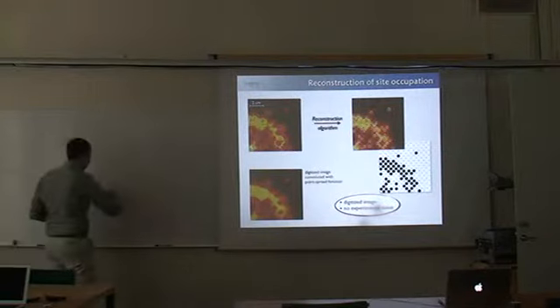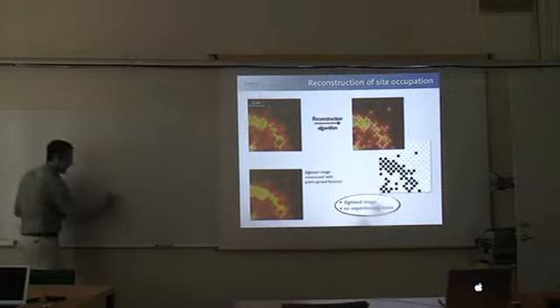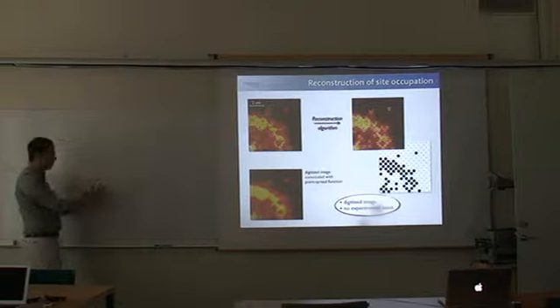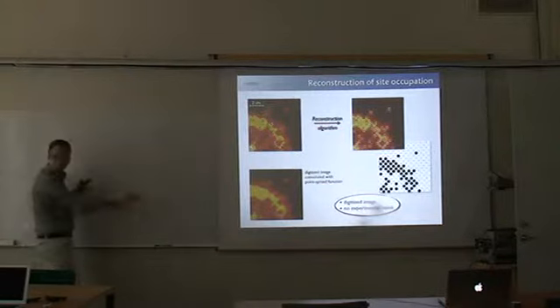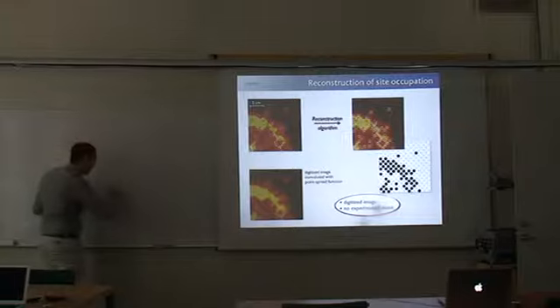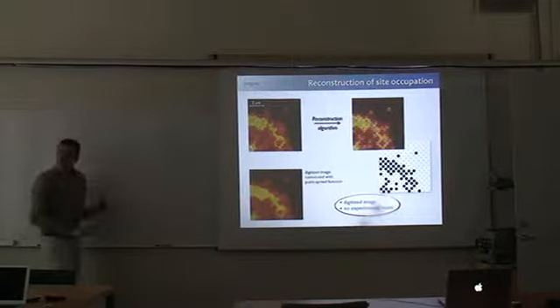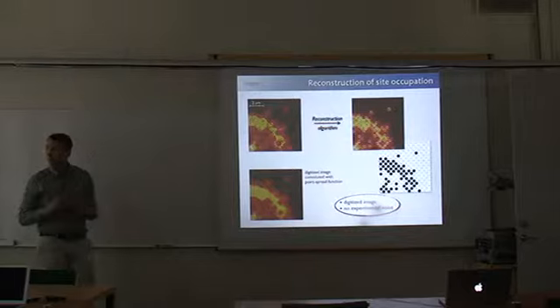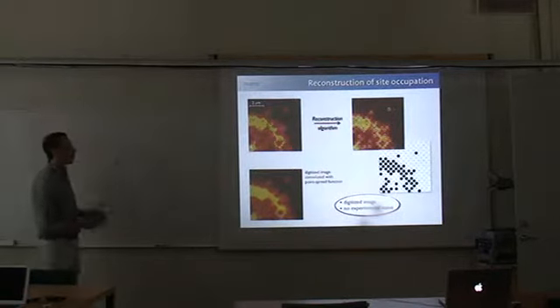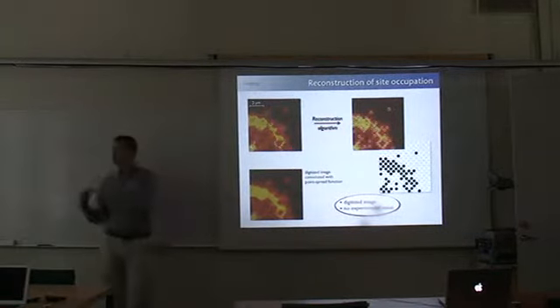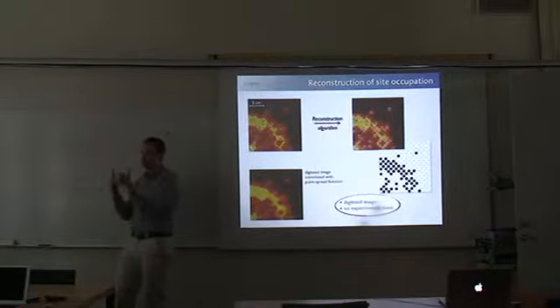No, absolutely. So what happens is, you have an atom, it's kind of like a delta function, imaged through our optical system with some point spread function. So this is a distribution of fluorescence that we get from a single atom. The next one on the neighboring site will overlap and will of course yield an increased fluorescence. Okay, so you first subtract red, then you subtract contributions of red to yellow and see what's left. What helps us are two things. If particles would not be on a lattice, and also we could have any populations, we would be lost. We could not reconstruct the atom number with very high fidelity.